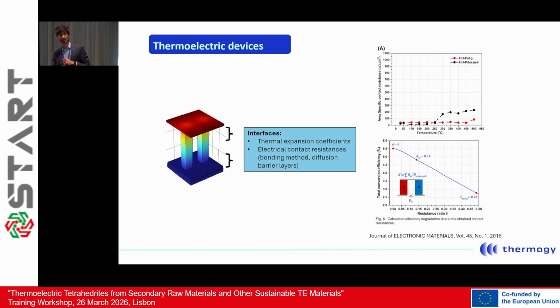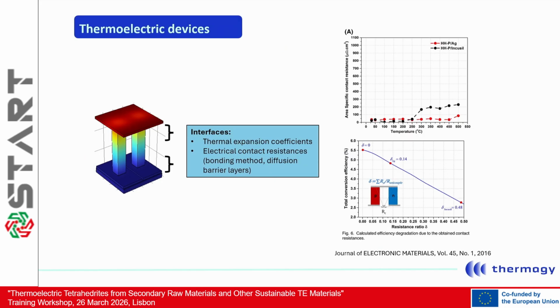you have to put it all together. So you also have the interfaces between these materials, as well as the top and the bottom end connectors. So that's what is basically transporting all the current through the entire device. And there, the thermal expansion coefficients of the interfacial layers, as well as the materials that you use for the active material and the end connectors, plays a role.